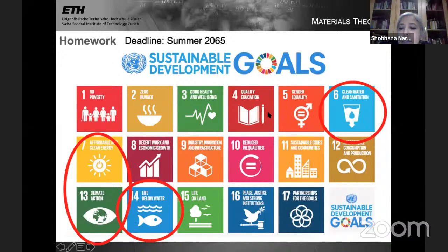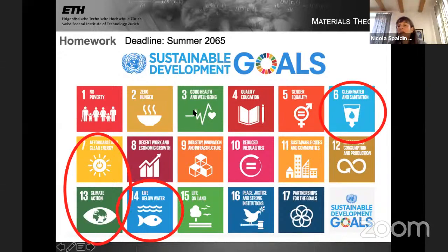He asked, what breakthrough can multiferroic materials make if DFT calculations help the experimental researchers who then synthesize it? That's a good question. What comes first, the DFT calculation or the experiment? I think in multiferroics, we have many examples where it's really going around. We first started thinking, how could one make a multiferroic? And we thought, bismuth could be good, and magnetic ions combining together. And actually, I remember our first DFT calculations, we proposed bismuth manganite for many good reasons, which turned out to be wrong. And so then the experimentalists said, okay, that didn't work. They tried bismuth ferrite. And then we were able to, with the data I showed you, explain why it had such a large polarization.